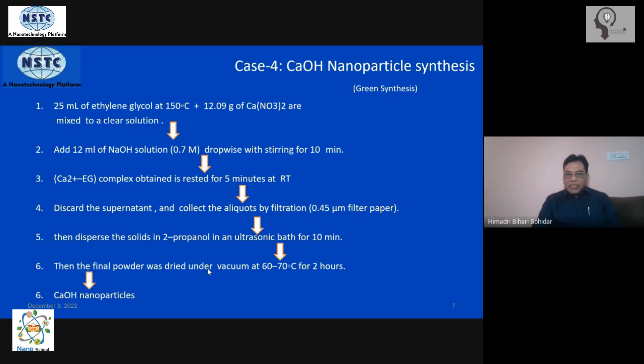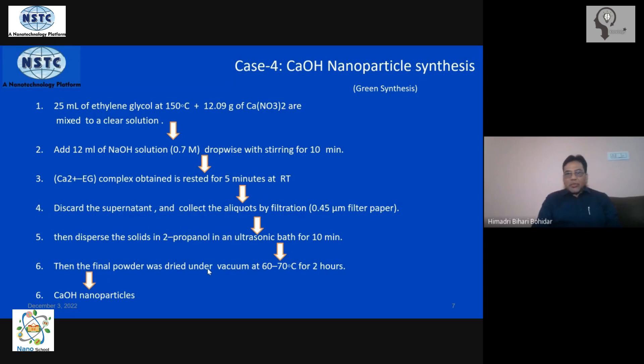Sodium hydroxide is then added to carry out the reduction process at the same concentration as used earlier. Mix it well to make a homogeneous preparation. The calcium ions from calcium nitrate combine with the ethylene glycol molecule to form a complex — this is the aliquot, the reactor product. Rest it for about 10 to 15 minutes at room temperature. It will settle at the bottom. Discard the supernatant and filter the aliquot using a 0.45 micron filter paper, standard in chemistry labs.